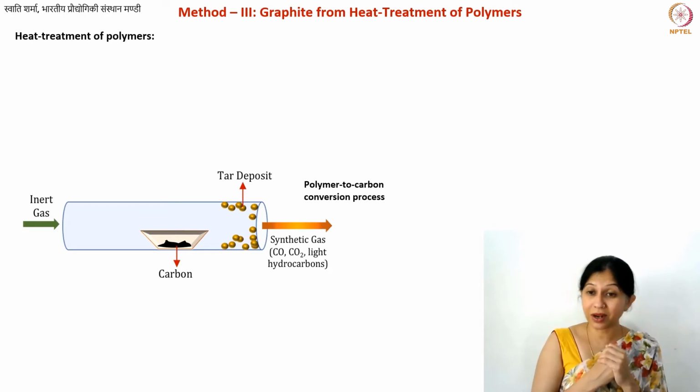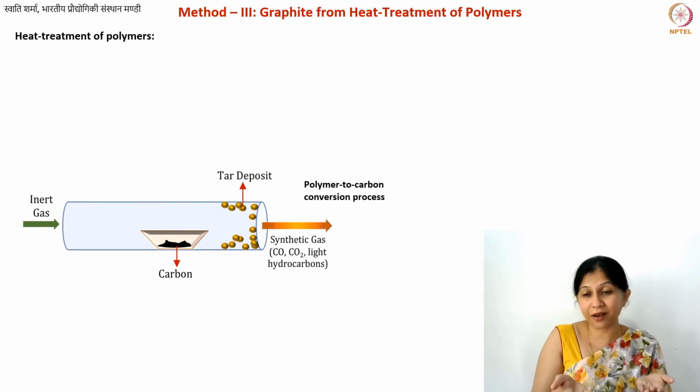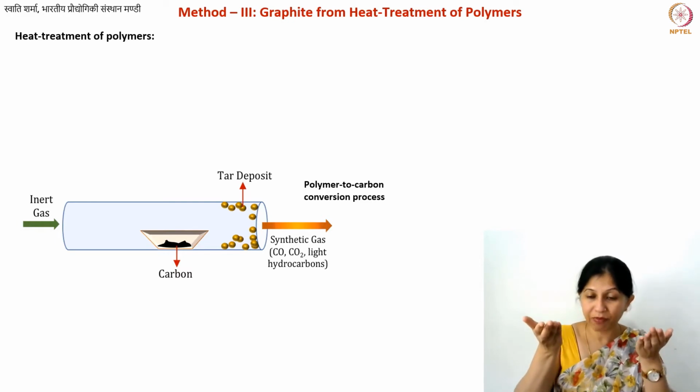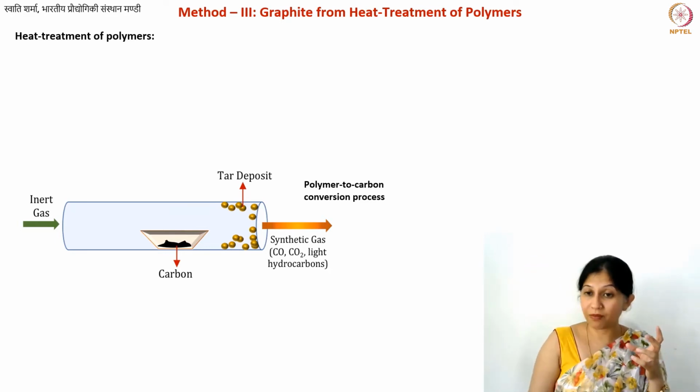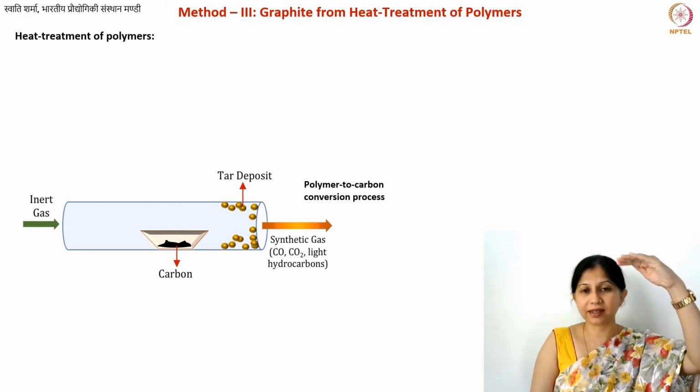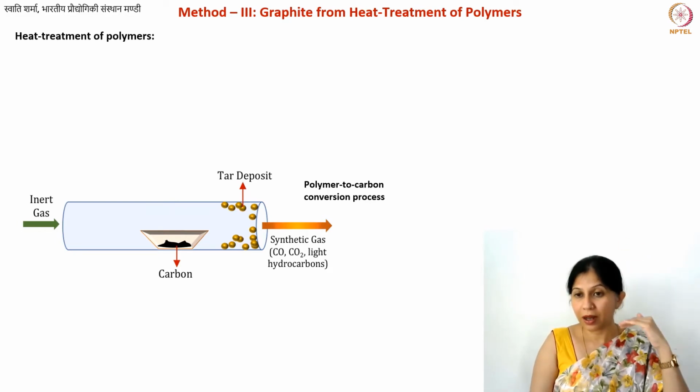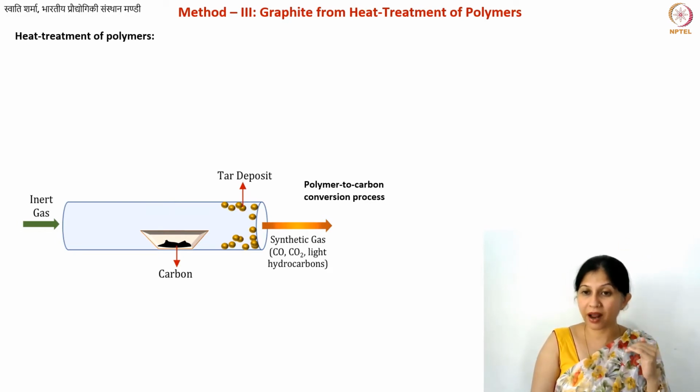But it's also like this oily, tarry material. So it's also not going to be a part of your solid carbon material. It is volatile enough that at 1200 degrees, let's say, it will be removed from your solid material. But then it's also not going away. Often it gets deposited onto the walls of your furnace. You will see some tarry deposits.